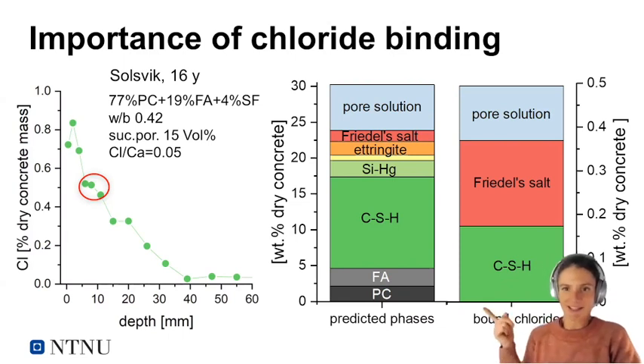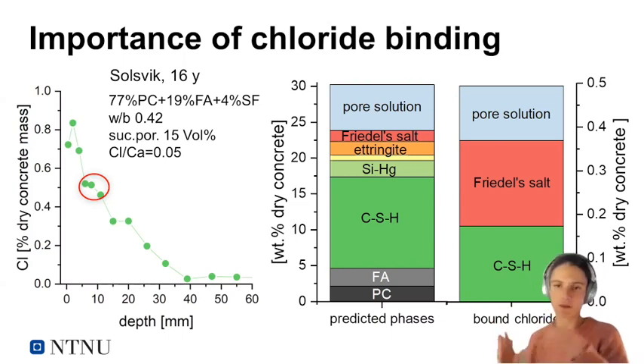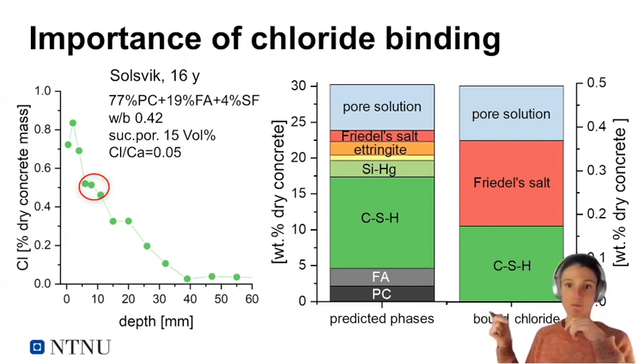And in order to do so, I again used my thermodynamic model and calculated what hydrate assemblage I would have, assuming a degree of reaction of 85% for my Portland cement, 30% for my fly ash, and that all silica fume has reacted. And then I get this hydrate assemblage. And I assume that all my AFm is Friedel salt, and I used the ideal stoichiometry of Friedel salt. Then that would represent this amount of chlorides in my Friedel salt. So that would stand for almost 0.2 weight% of the chlorides in the section indicated with the red circle.